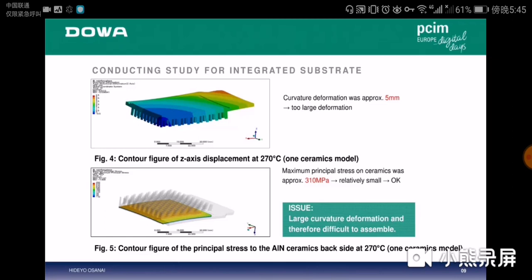Figure 5 shows the stress generated in the aluminum nitride at this time. It indicates that a principal stress of approximately 310 megapascals occurs, which is relatively small. However, because of the large curvature deformation, it is difficult to assemble.